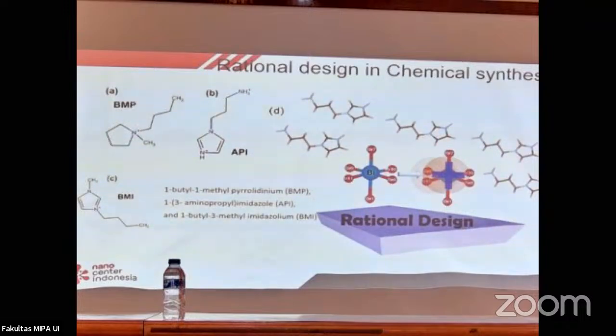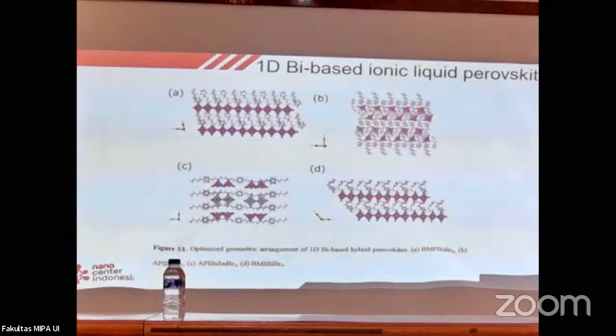For those who know about ionic liquids, they have this kind of specificity in which you have one heteroatom that is normally situated in, for example, a cyclic part, and then you have some very long tails. And we came up with these three different ligands. The pyrrolidinium and imidazole ligands we use to grow a perovskite, and the whole idea, based on Ricky's calculations, is that these three ligands can give a very nice output to demonstrate the polaronic state of the bismuth perovskite.